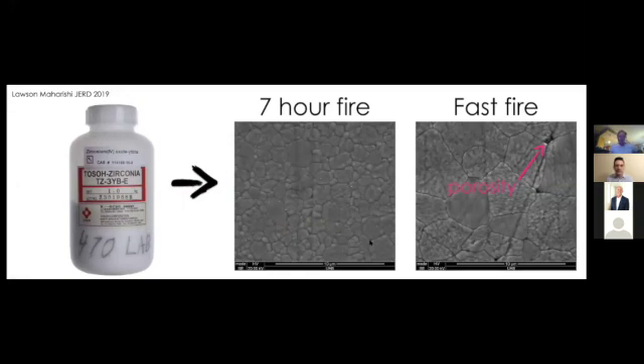There's also, for the CEREC type of people, the speed fires now where they can do the fast fire in 20 minutes. And we tested those types of zirconia. What we found out was that if you get materials that are made for speed fire, they had the same properties whether they were conventionally fired or speed fired. They didn't lose any of the properties.